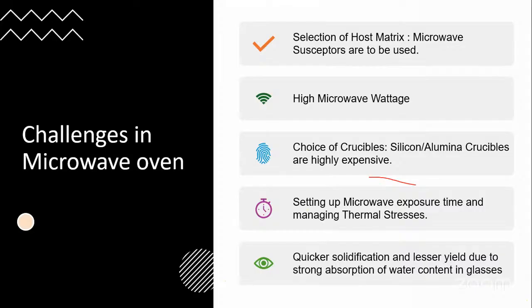And the most important challenge is, the moment there you can see a reddish color found in the crucible. Here, the crucible doesn't become red, but only the glass has undergone its molten phase. So the moment you remove it outside the microwave environment, it quickly solidifies. So the yield that you get from microwave is also less, but there is an advantage, since microwaves strongly absorb any water content at 2.45 gigahertz. Therefore, the entire water content present over there gets absorbed completely. So that is where you find this challenging.